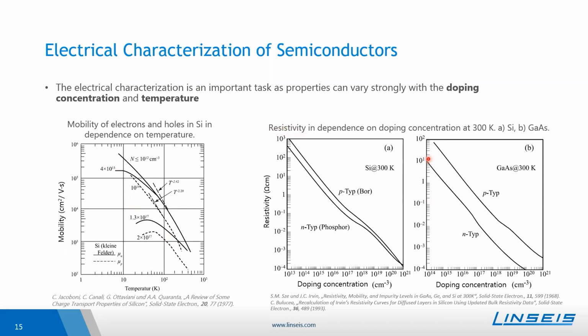On the right, you see an example of the resistivity and its dependence on the doping concentration at room temperature. So here only the resistivity and its dependence on the doping concentration is plotted, where you can see that the N-type and P-type doped silicon behave differently, but clearly both depend on the doping concentration, so that the more impurities are brought in, the lower the resistivity will be. And here also for the gallium arsenide case, here even the N-type and the P-type differ more strongly in resistivity, but both also show a clear dependence on the doping concentration.